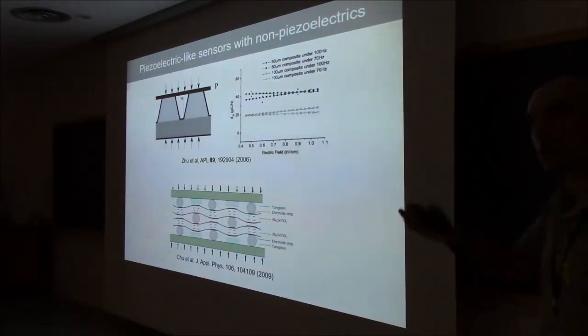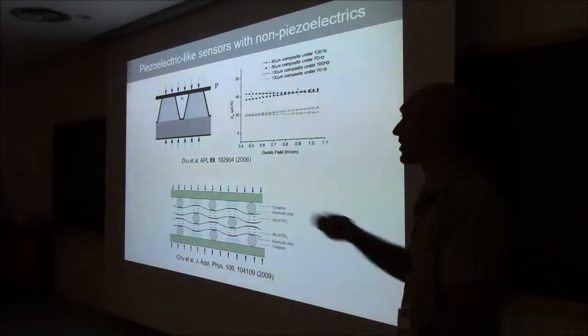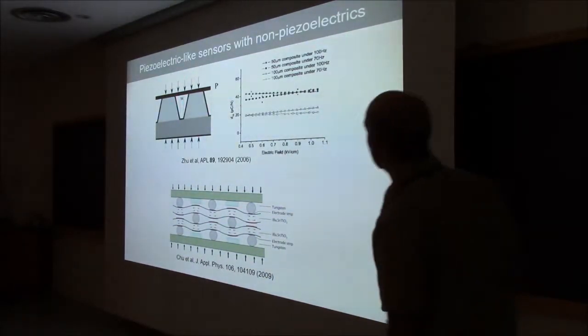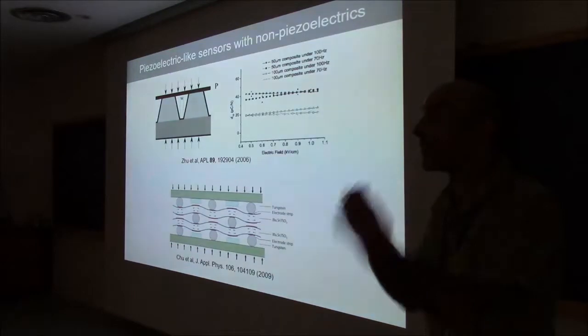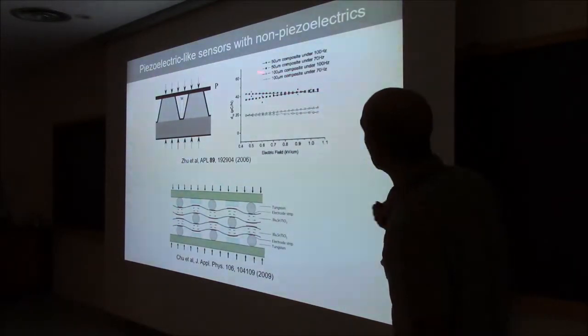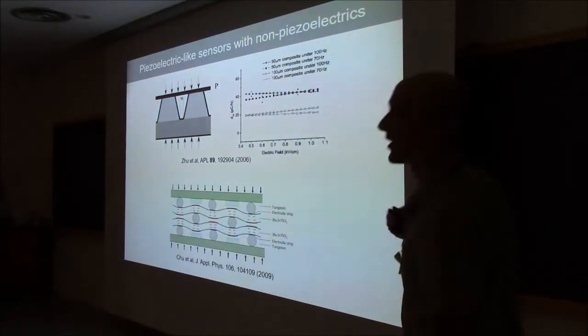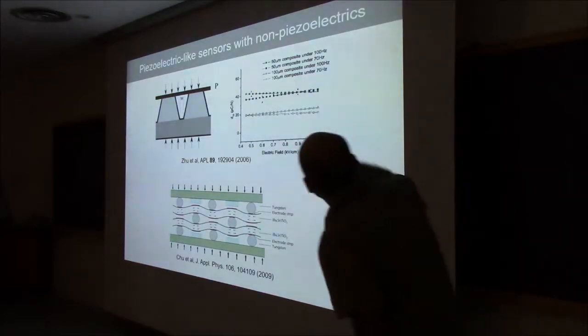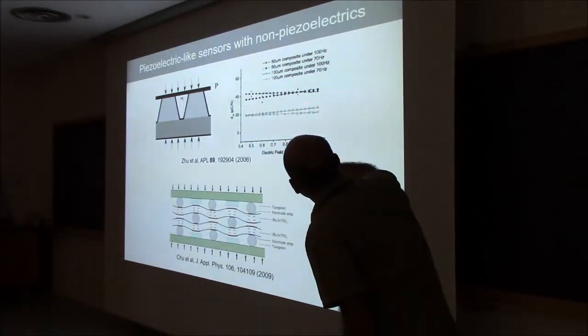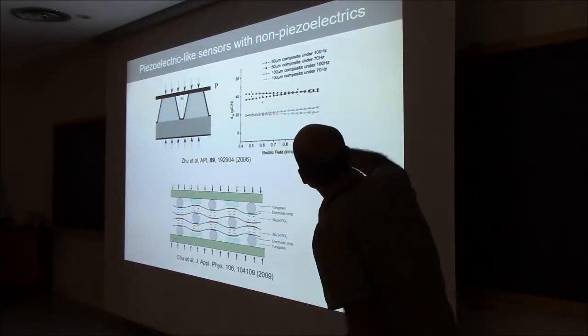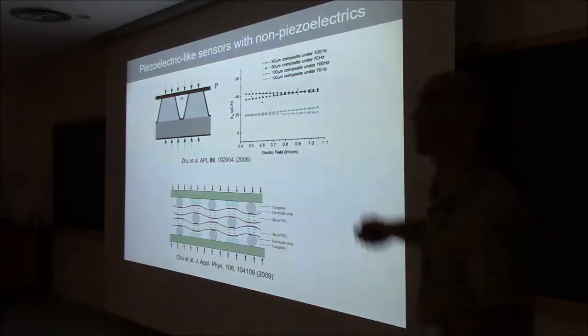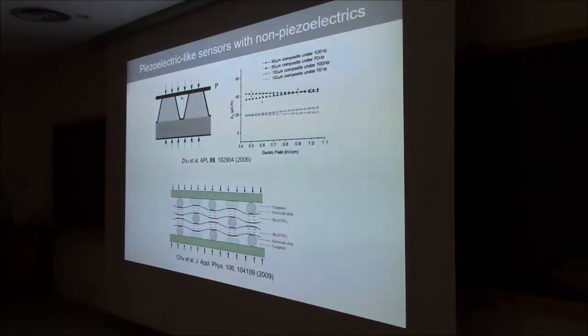Moreover, as I told you, this thing is inversely proportional to size. He took the same truncated pyramids and made them half as big, and the effective piezoelectric coefficient, as you saw, was twice as big. Maybe you can read this, but this corresponds to 100 micron pyramids, and this corresponds to 50 micron pyramids. That was a real experiment.